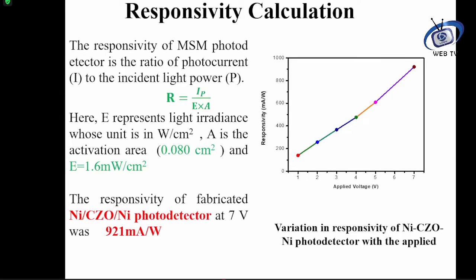This is I over E times A. I is the photocurrent, divided by E, the light irradiance, which is the UV light, and A is the activation area. And the responsivity of the fabricated nickel, where nickel is the metal film deposited onto the film for the connection, so contact. So for nickel, zinc copper oxide, nickel photodetectors at 7 volt, we have 921 milliampere per watt, which is very good